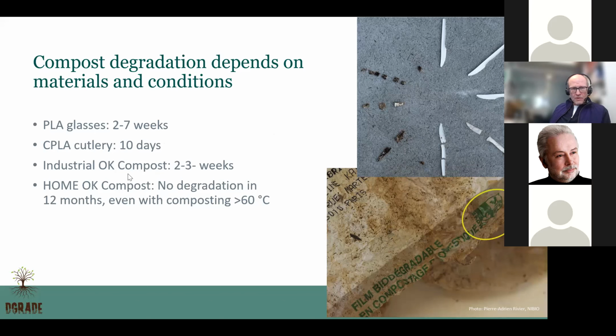What we added of these waste bags labeled industrial OK compost also degraded relatively fast in hot composting, while the home OK compost, you can even see the label here, after incubation in the compost for 1 year, they don't degrade at all, it seems, and they don't degrade very much even in hot composting. We tested this at 60-65 degrees, and they don't degrade much there, unfortunately.